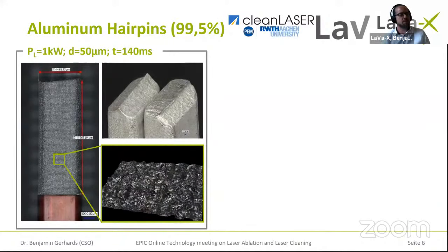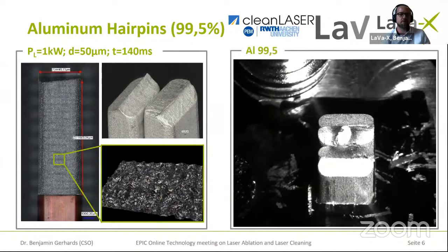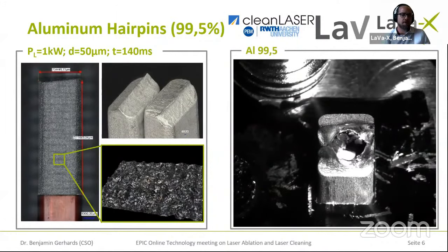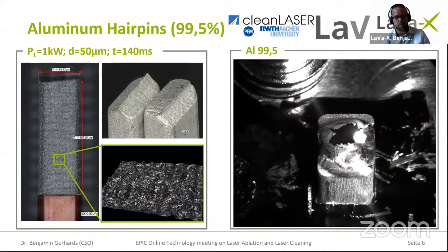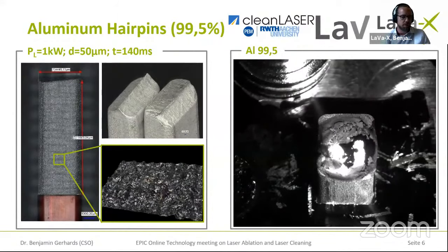And the last example that I want to show you is, again, in cooperation with cleanLASER, and in this case, PEM of RWTH Aachen. It was those aluminum pins that Tobias also showed. And I want to show you another high-speed video of this because it's quite impressive in my mind. If you know something about laser beam welding of aluminum, then you know that aluminum is very, very susceptible for pore formation. And the first thing I want to draw your attention to is that there are nearly no spatters that are occurring.